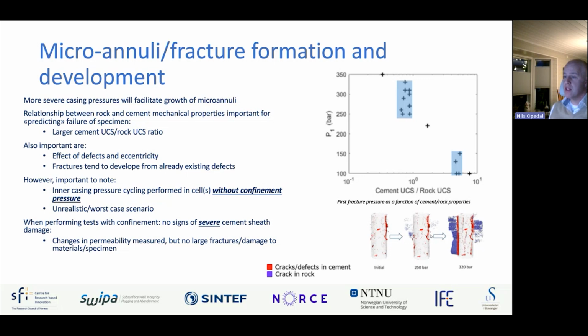In terms of relevance for the industry, it should be noted that some of these tests have been performed without confinement pressure. That means the specimens or materials will behave differently from how they would in a wellbore. So when we do a test like this and get results like this, our understanding is that this is, I won't say unrealistic, but an absolute worst case scenario. Because for most wells, you will not have a pressure difference of 200, 300 bars, or at least you will have a confinement pressure from the surrounding rock in your well.